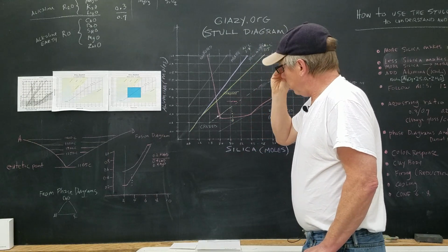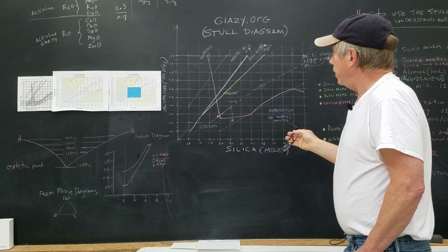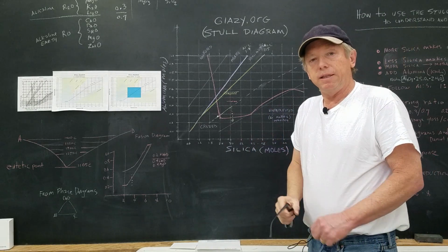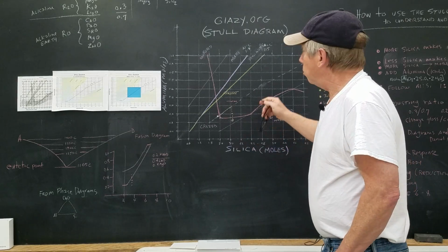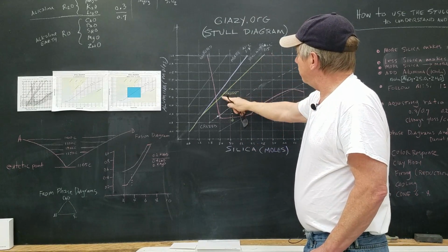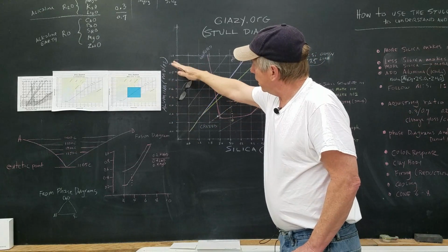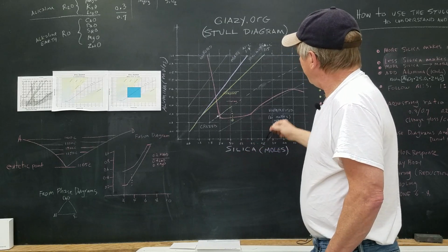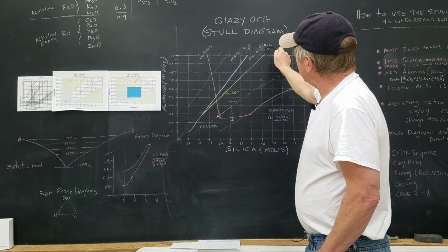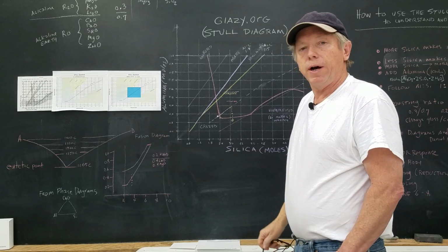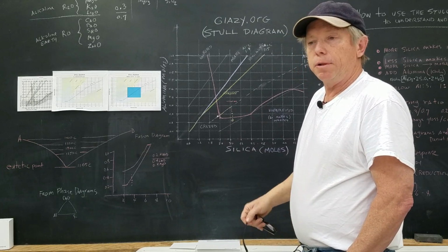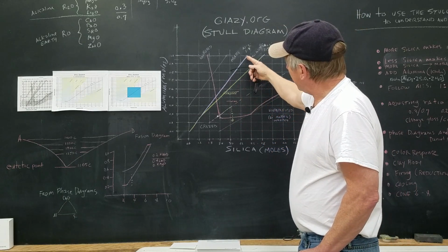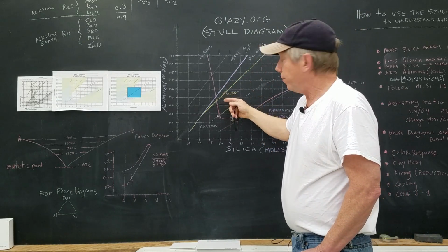Now, we'd like to know how to understand our glazes better and manipulate them using this chart. So what we want to concentrate on is these lines. Here alumina is increasing, here silica is increasing, and here's a line, 1 to 5, that's alumina to silica. If you have a 1 to 5 ratio, that's probably going to be a semi-matte glaze, or pushing towards a matte glaze. 1 to 4 is going to be matte, and that's what this chart shows you.